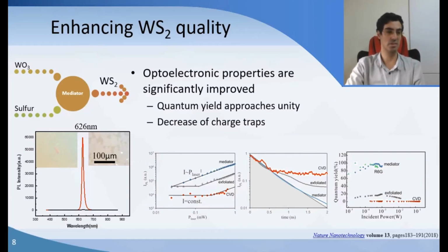Another way to check the decreased importance of charge traps is that mediator-assisted CVD has just a single lifetime, whereas materials grown by other processes have a fast decay and then a slow decay because carriers are getting trapped in trap states. That yields materials that are significantly better in optoelectronics. We're getting quantum yields that are near unity for mediator-assisted growth, whereas for both exfoliated and CVD-grown WS2, the quantum yield is much lower because of the presence of traps.